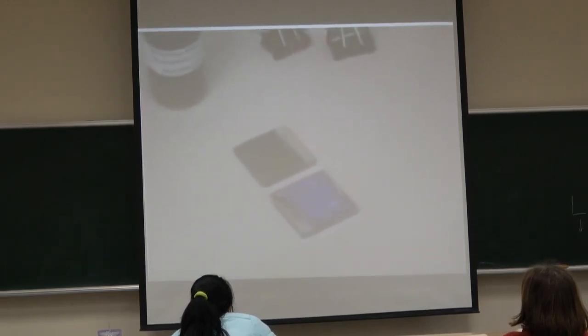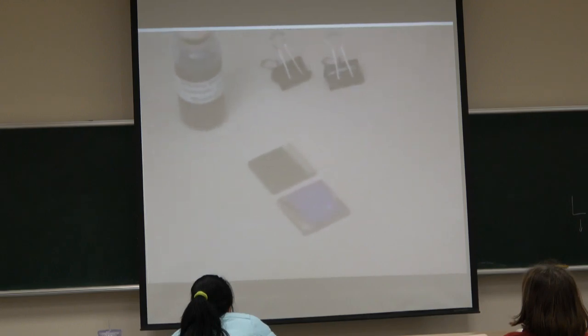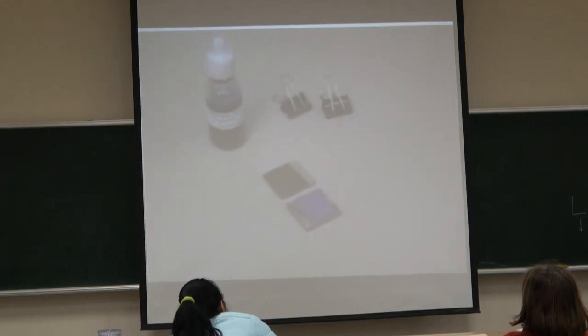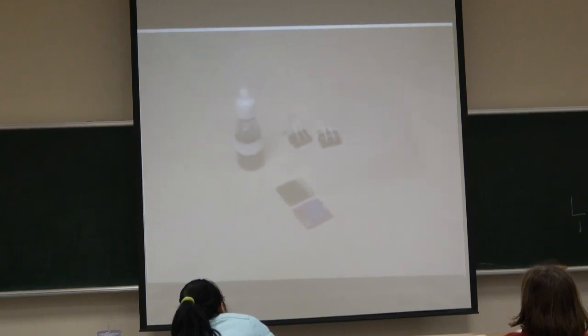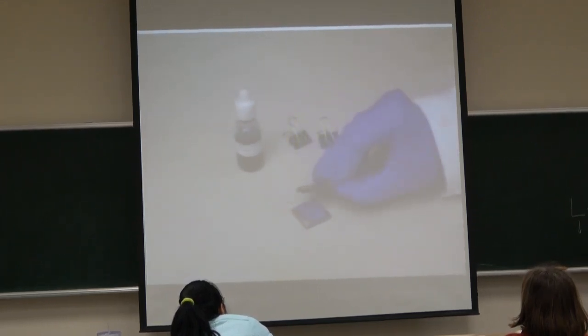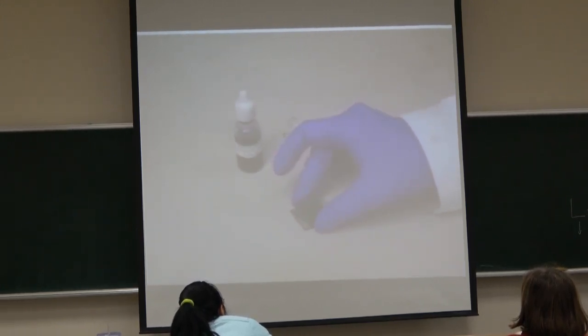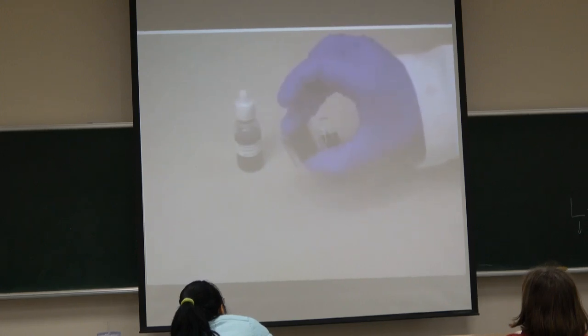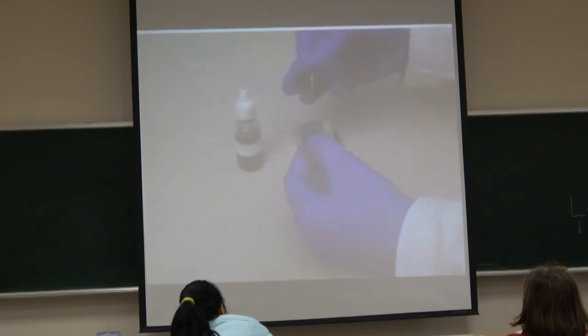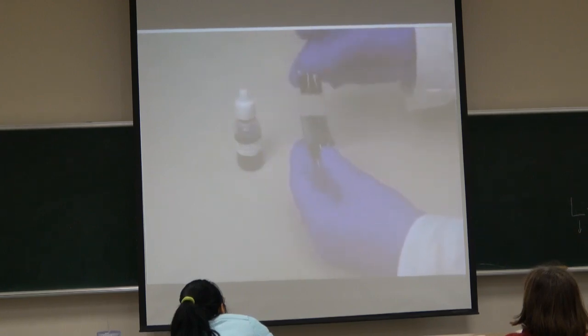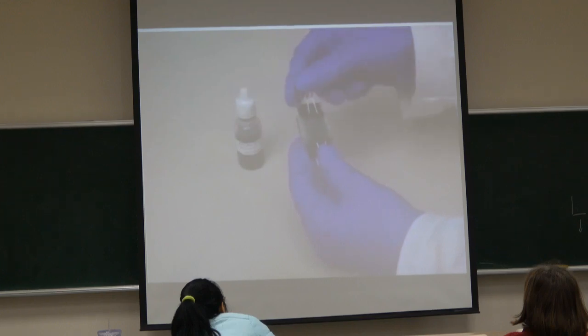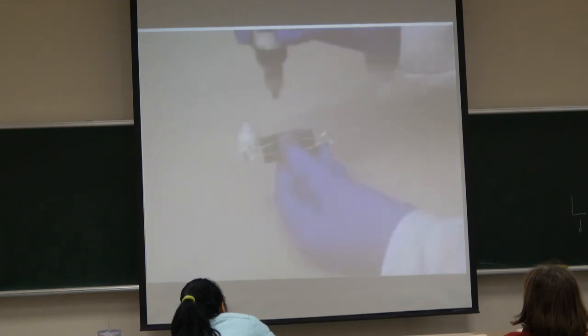Step 3. Place the dry titanium dioxide coated slide on a flat surface so that the titanium dioxide coated section is face up. Place the carbon coated slide face down on top of the titanium dioxide slide so that the coating completely covers the titanium dioxide coating, leaving a 4 mm strip exposed on each slide. Step 4. Pick up the two slides in this orientation, being careful not to let them move. Clip the edges, the ones that do not have the 4 mm strip exposed, together on both sides with 2 binder clips. Step 5.